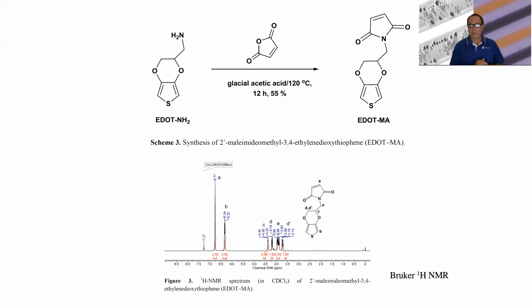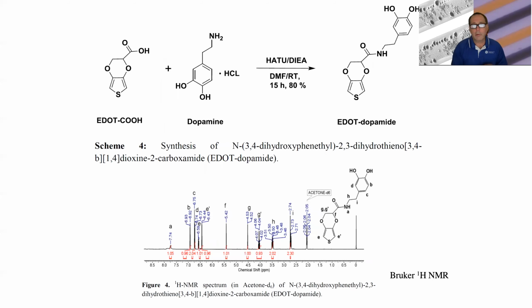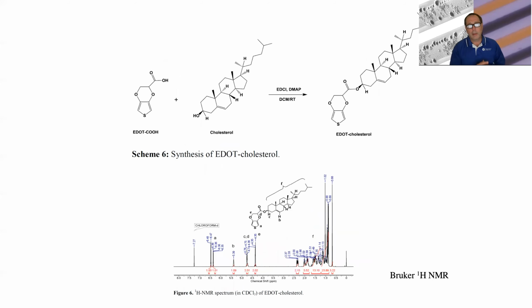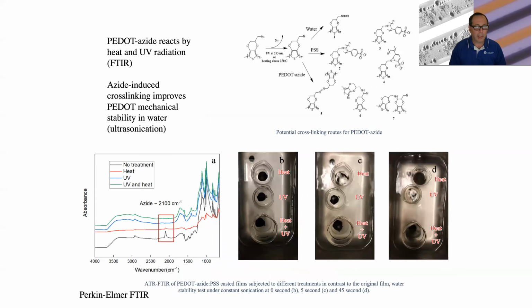So just some results showing that we've obtained the molecules that we're after. Here is the synthesis route and the proton NMR that confirms that we've made the EDOT maleimide. Here is the synthesis route for putting dopamine on. The dopamine itself, an interesting molecule, can be used as the precursor for synthetic melanins and is found in the body naturally. And again, the proton NMR confirming that we got it. And here's the EDOT cholesterol showing that we've made thiophenes with this surface active and potentially liquid crystalline cholesterol unit on the side.